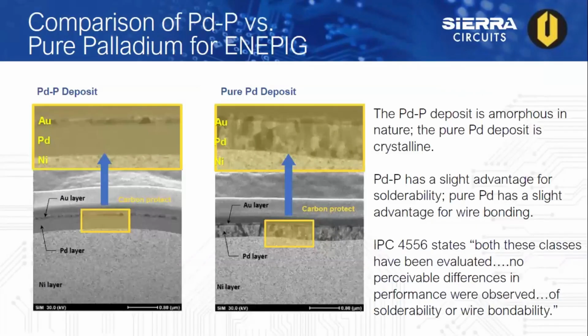Now here we have a comparison between palladium phosphorus and pure palladium in ENEPIG. There are differences in the deposit structure, as you can see in the cross-section images. Palladium phosphorus is amorphous in nature, while pure palladium is crystalline in nature. Palladium phosphorus deposit has a slight advantage for solderability, while pure palladium has a slight advantage for wire bonding.